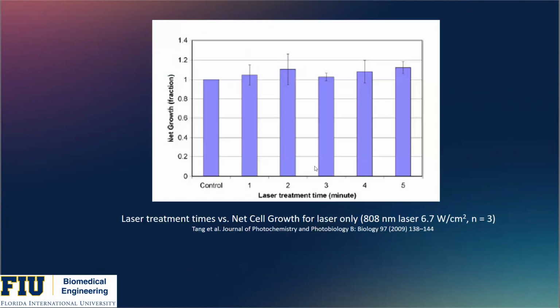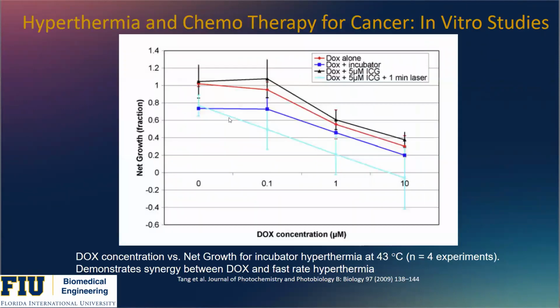Now, of course, we need to show that the laser itself doesn't induce damage to the cells. So we grew cells and exposed them to the same laser with the same energy fluence, and showed that even after 5 minutes of exposure, there was no effect on the cells. Here we looked at the combination of hyperthermia and chemotherapy.